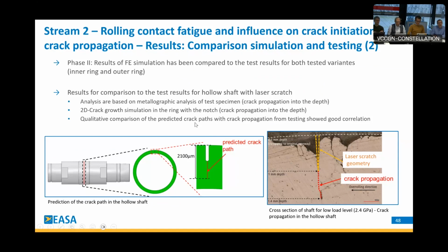Each analysis is again based on metallographic analysis of the test specimen to check for the crack propagation in the depth. It's the 2D crack growth simulation, as I mentioned before, in the ring with the notch, also to see what is happening in the depth. And we compared qualitatively both simulation and the testing, and as you can see here on the pictures, it's also correlating quite well. We have the predicted direction of the growth.